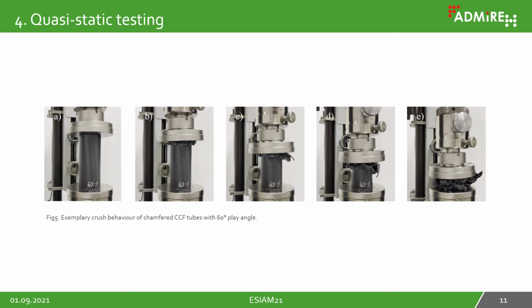Figure 5 exemplarily shows the crush behavior of one continuous carbon fiber crash tube with a 60-degree fiber angle. In the first two pictures, you can see the start of the damage triggering process until shortly after the elastic region. In the last three pictures, figure C to E, the progressively crushed continuous carbon fiber crash tube is shown.